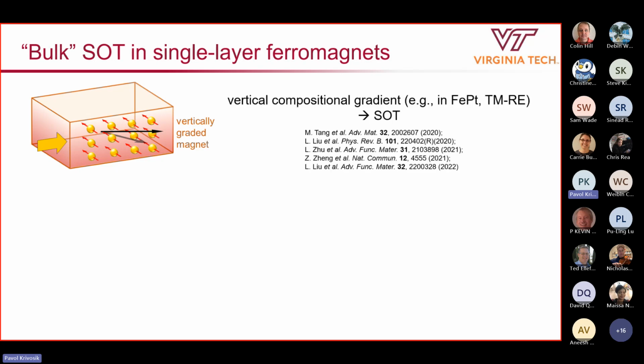So by the time we got started on this particular work, there already were quite a few studies reporting spin orbit torques, in some cases even perpendicular magnetic switching, in ferromagnetic alloys with vertical compositional gradients. So these were reported in materials like iron platinum and TMRE, these are transition metal rare earth alloys.